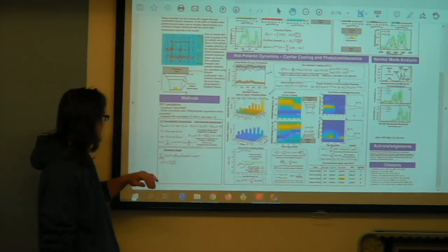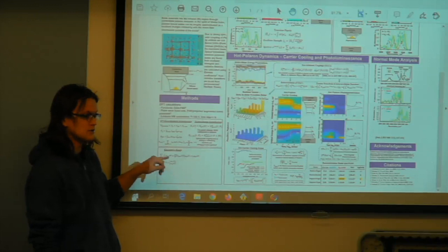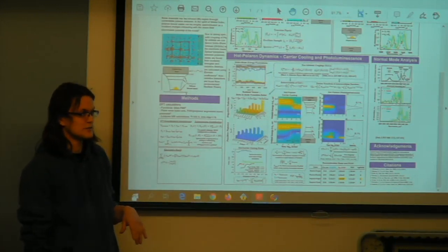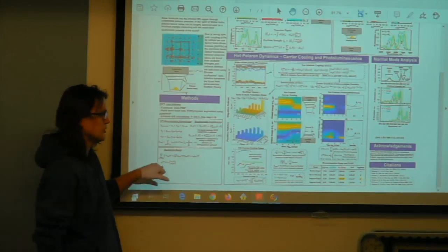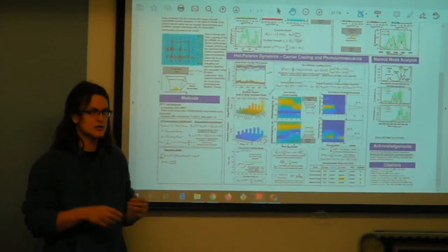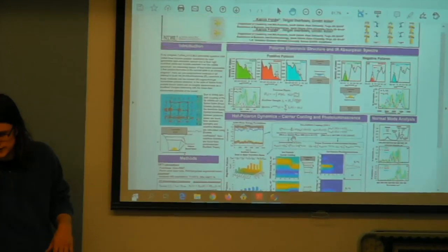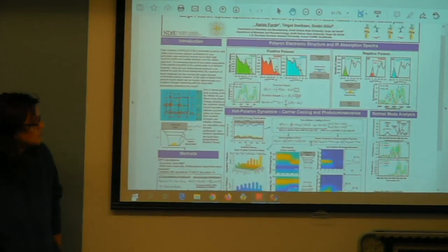That's kind of how we describe polaron formation in the system. And then technical details. In perovskites, you have strong spin-orbit coupling because the lead states involve 6p orbitals, so they have large angular momentum. In DFT, to incorporate that effect, you have to use spinor orbitals. Those are the electronic states that we use to compute the spectra and the dynamics. So moving on to spectra.